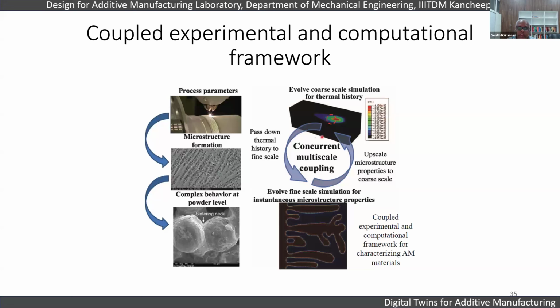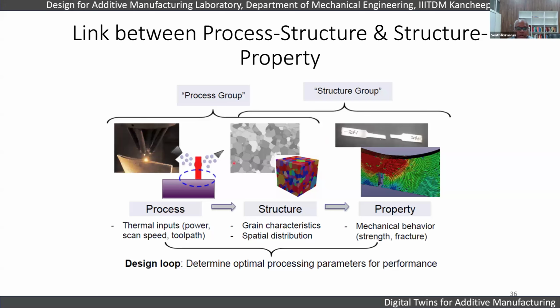And the linkage is always very difficult to get. For example, you have different process groups like DED, lasers, electron beam, different materials, right? So different thermal inputs and different kinds of process parameters, which result in different grain structures. And you have to test them using coupon testing, destructive testing to understand their mechanical behavior. So the design loop involves finding the optimal process parameters and linking process to performance to property. So a complete link between process, structure, property needs to be established.